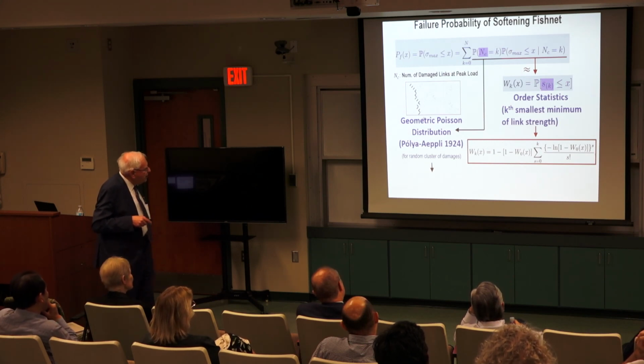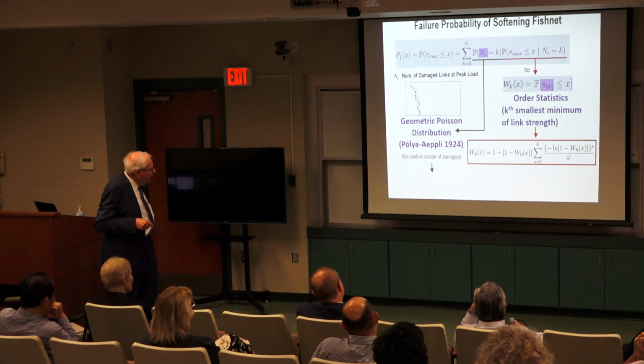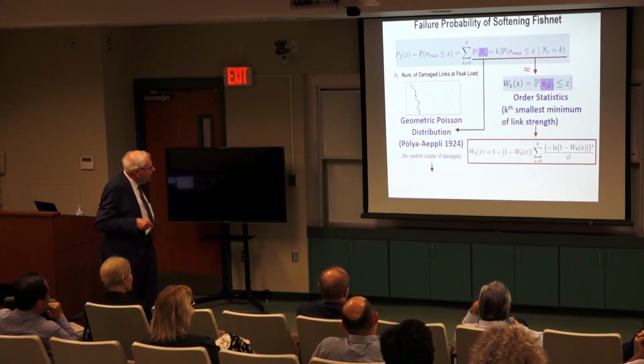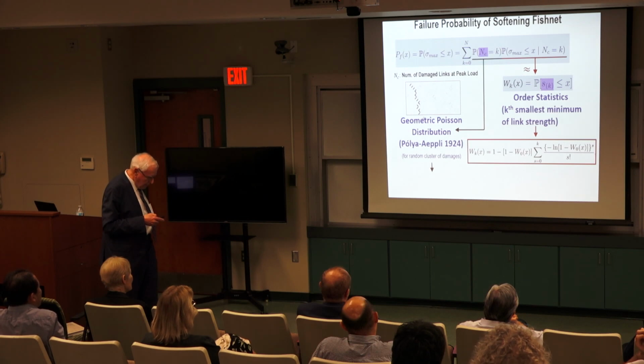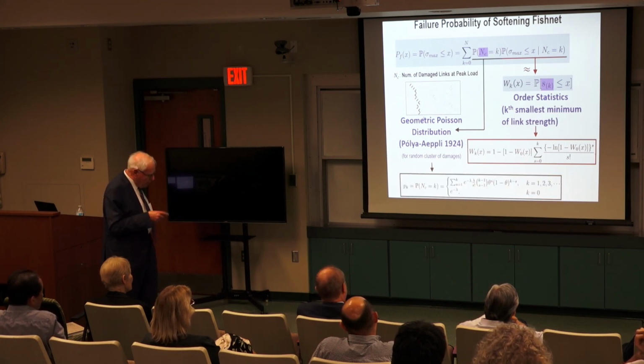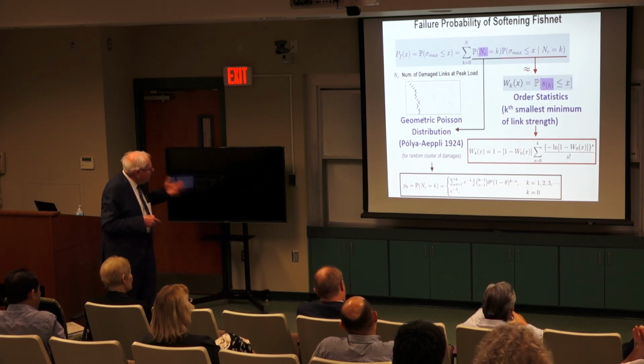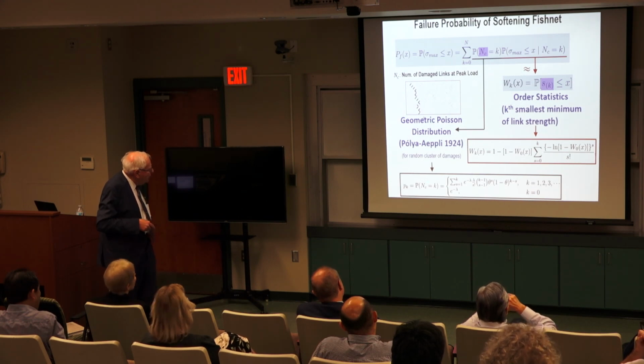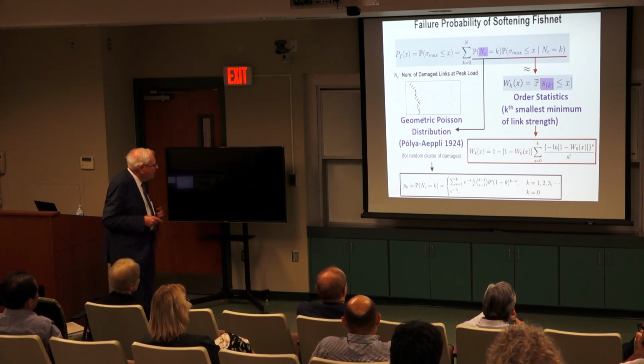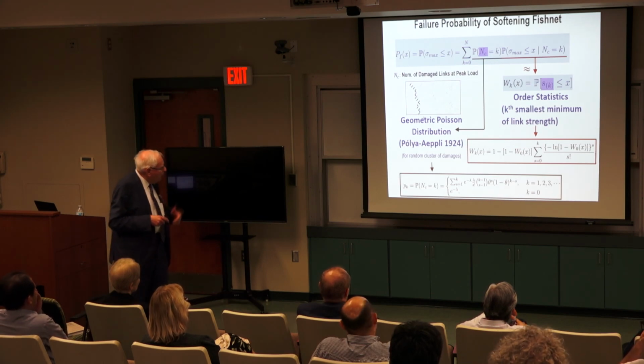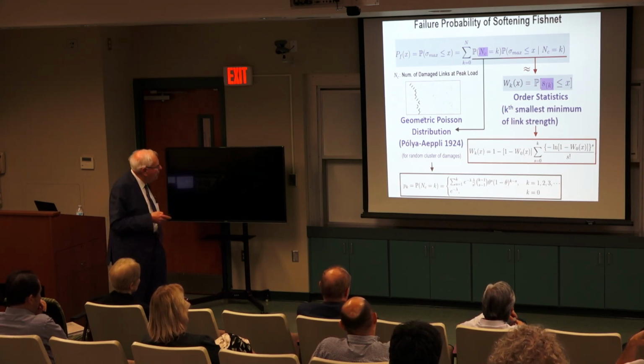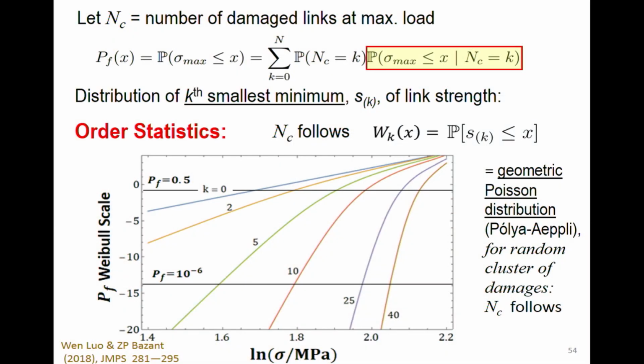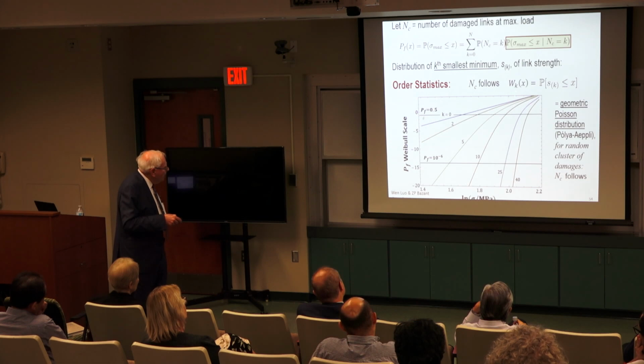So order statistics, there's a book on it, in fact several books, gives you some formula, which is not difficult. That's here, how to calculate it. And for the distribution of the number of jumps, this is like arrival statistics. Actually, it's a geometric Poisson distribution. It's another formula. So that's what we discovered by reading more literature on this kind of behavior, and we put it into calculations. And then, using order statistics, we find the following. This again, Weibull scale, Weibull distribution. You have one jump down.